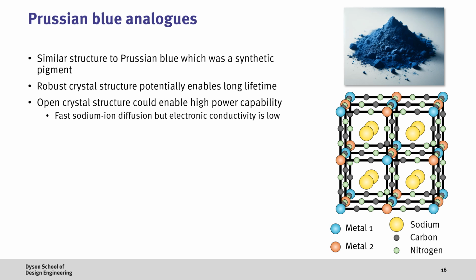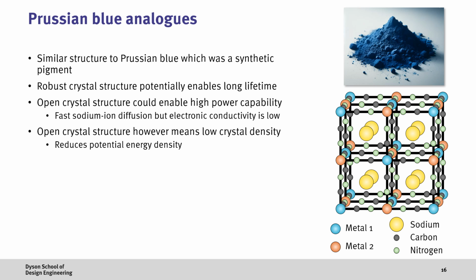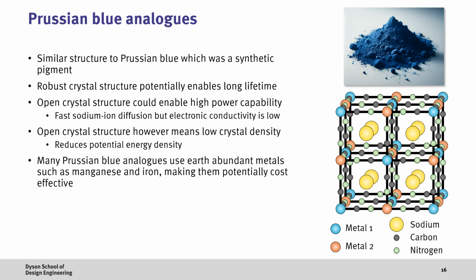They generally have a robust crystal structure which potentially enables long lifetime, with this open structure enabling good sodium-ion conductivity, but the poor electronic conductivity needs to be overcome for high power capability. A drawback of this open structure, however, is that it reduces the energy density of the material. However, many Prussian blue analogues use earth-abundant metals such as manganese and iron, making them potentially quite low cost.